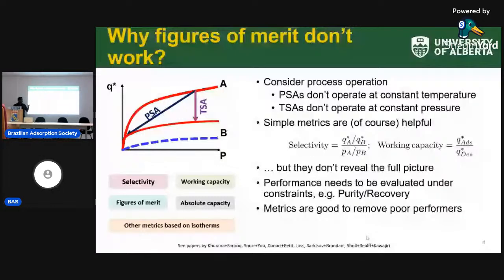And consistently, we have seen that at least for CO2 capture, at least with pressure swing adsorption, the best materials are the ones that have almost zero nitrogen affinity. And that is also important because if you're someone working in this area, always please report also the nitrogen adsorption isotherm because it is very, very important. It is, in fact, I would say, as important as the CO2 isotherm. Right? We are dealing with a separation problem.